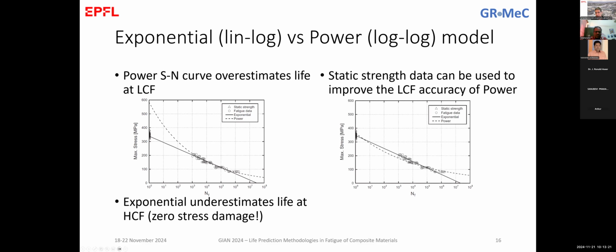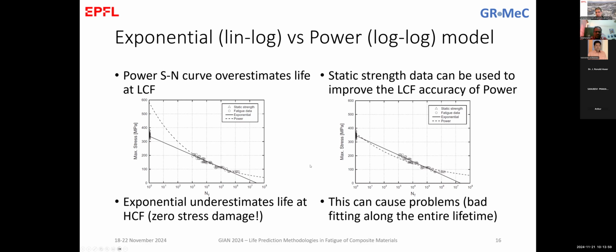The same we can see in this range. These are the same data sets. And in this case, we used the static strength data to fit the material performance. You see that we lose accuracy with the power model, but it's now better in the entire lifetime. Here again, the exponential, so the lin-log model, has the same issue of cutting the axis at a certain number of large material loading cycles.